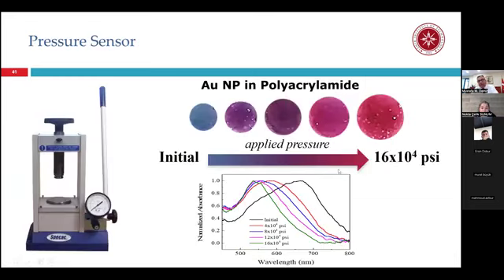So we are using polyacrylamide. It's transparent, it is biocompatible, and it is a self-healing polymer. So gold clusters are mixed with polyacrylamide. You have a blue composite film, like litmus paper. Then you apply a certain amount of pressure, okay? So 40, 80, 120, and 160 PSI, okay? For application of pressure, we are using a very simple apparatus. You can find this apparatus in any vibrational spectroscopy lab for sample preparation of FTIR samples. It is possible to apply pressure on the composite system.